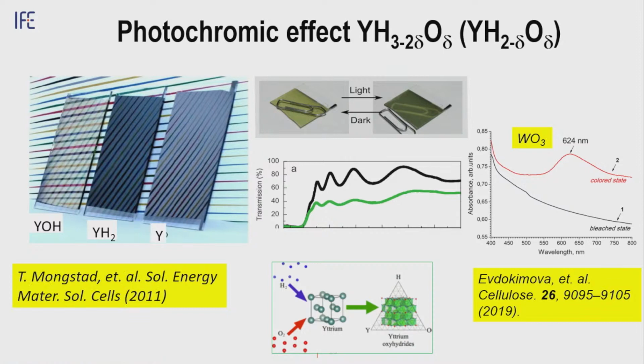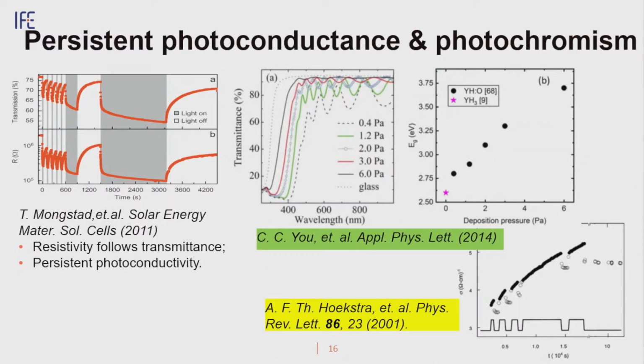If we measure optical properties, this is the transmittance spectrum corresponding to the transparent state. And in the colored state, it becomes like this. This is what I mentioned in the case of, for example, tungsten oxide. This is light absorption in the clear state, but when it's illuminated, then mid-gap states will be formed that will block visible light. Here, as you see, there is no blockage of visible light.